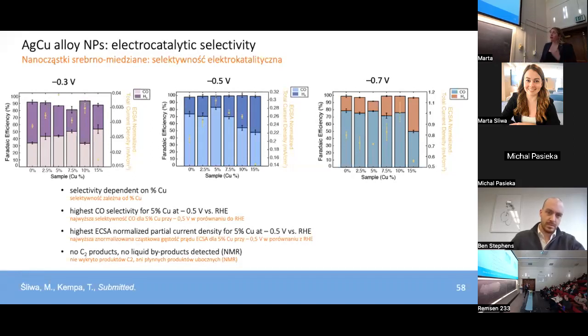We also looked at the selectivity of the CO over the other products that are formed in this system. The largest byproduct that we get is hydrogen. Again, we see that there is a ratio between the carbon monoxide and the hydrogen, with more carbon monoxide, again unsurprisingly, being formed at those more negative voltages. But again, we see the highest suppression of that hydrogen byproduct and the highest Faraday efficiency for the carbon monoxide product at this 5% copper and silver alloy. If we increase at the same voltage to 15% copper, we see a drop of that Faraday efficiency to close to 50%. So we attribute that overall reduction in the performance for the CO product to potentially the formation of